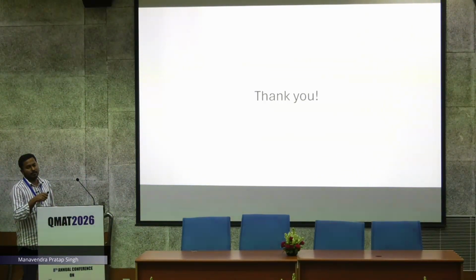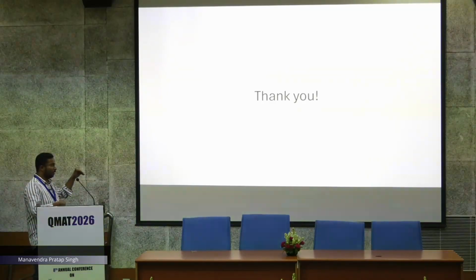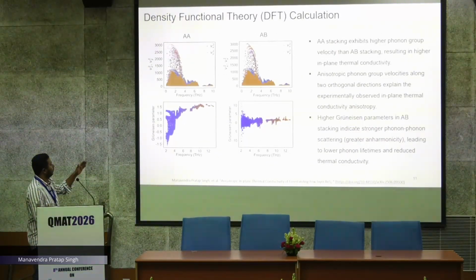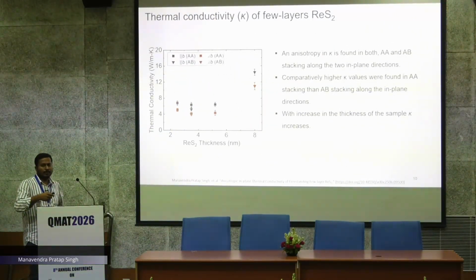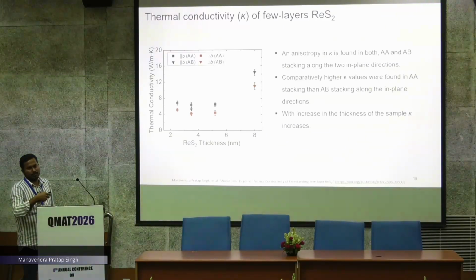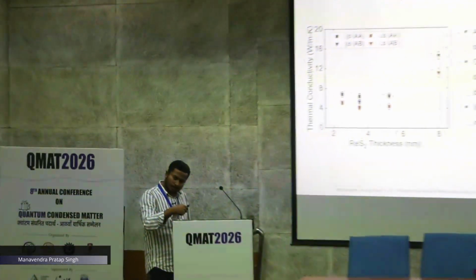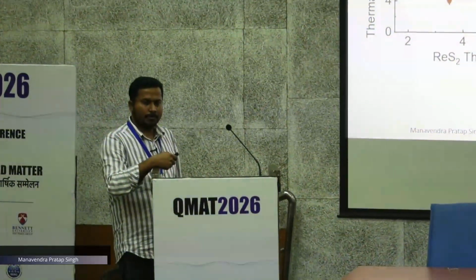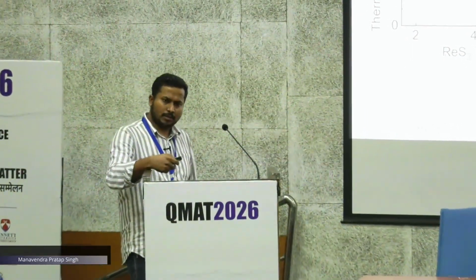So is the thermal conductivity lower than, say, bulk materials? Yeah, we can see the trend: increasing the thickness will increase the thermal conductivity. But it will sometimes saturate also at higher thickness, while at lower thicknesses it has a lower thermal conductivity. So this thermal conductivity you have measured by a technique, say Raman? Raman spectroscopy. Is it comparable to other conventional techniques? Yeah, it is.